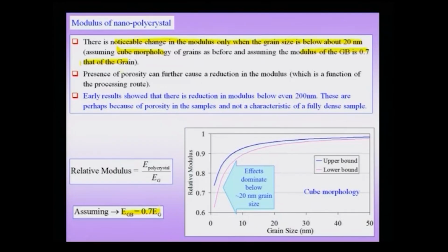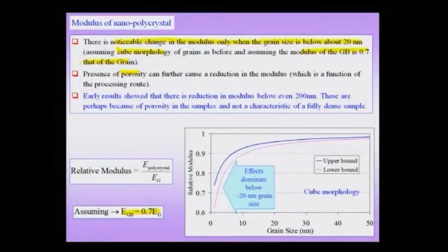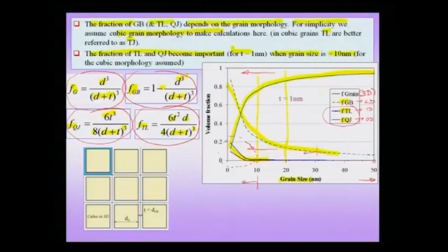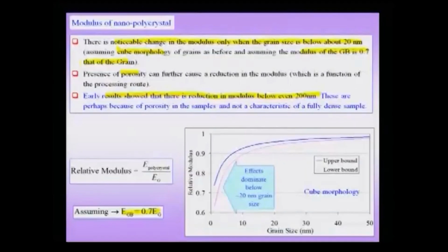And as before, we ignore porosity in the material, because as we shall see in the next slide, porosity could be a serious issue in very many problems. Early results showed that there is a reduction in modulus below even about 200 nanometers, the region where we have already seen that grain boundaries and other kinds of entities do not play an important role, but they did observe some reduction in modulus when they were already below 200 nanometers. And if you remember the slide from before, all the drastic changes seem to happen only below about 20 nanometers and not below about 200 nanometers.